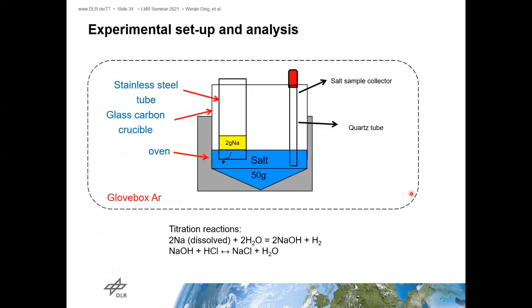Here it shows the setup and the analysis method to measure the sodium solubility. We use a glassy carbon crucible to contain the salt, and a stainless steel container for the sodium metal. We heat it to high temperature, and the sodium dissolves in the salt. We do several measurements, and usually after 1 hour the solubility is already at its highest. Then we do the titration measurement. We put the salt and dissolve it in water, and it has such reactions. Sodium hydroxide will be produced, and we use HCl to do the titration. Then from the titration value, we can know the sodium metal solubility.